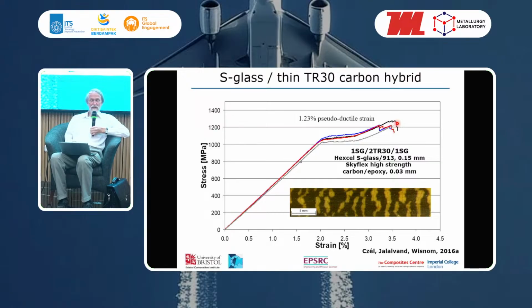And what's interesting in this case is that we've got 1.2% additional pseudoductile strain over and above what would happen if we just went up with the same straight line. This value here is the 1.2% extra pseudoductile strain. But as well as that pseudoductile strain, the appearance of the specimen is quite interesting, because this specimen is black to start with because it's carbon, but when the carbon starts to break, you get a little bit of delamination and you see these yellow patches appear.